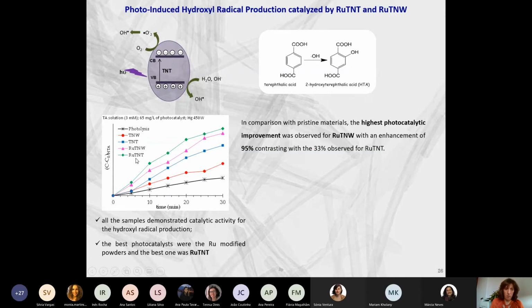And as you can see here, when we turn on the lamp, we can see that, in fact, our samples with ruthenium are better photocatalysts for this process than the ones without ruthenium. But of course, these two are also catalytic, but the ones with ruthenium are the best ones. And the best one is the titanate nanotubes with ruthenium. Okay?